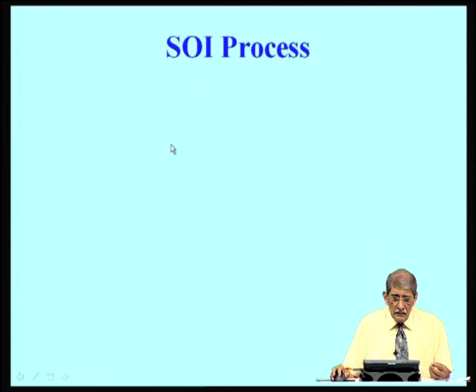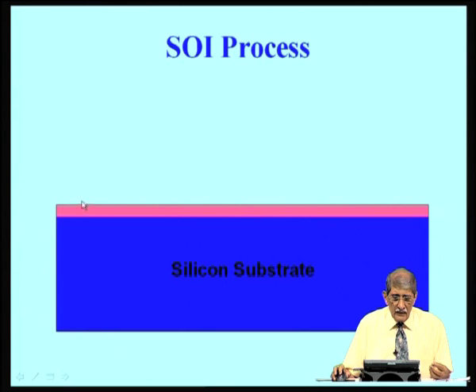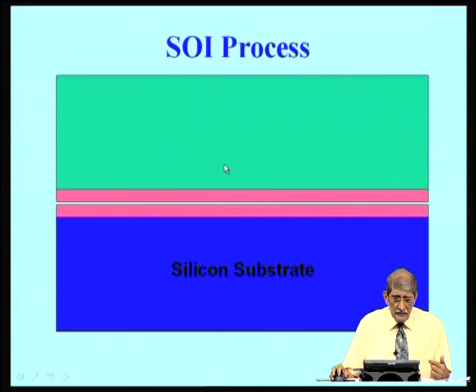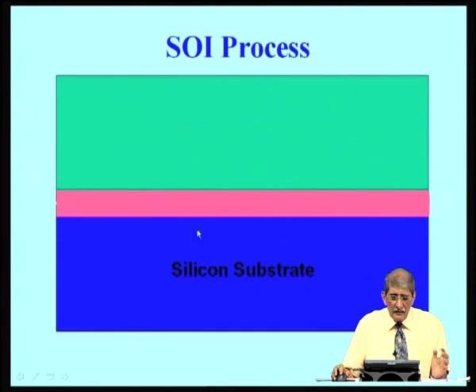Take one wafer, oxidize the wafer, okay, the process to make the SOI layer. Take another wafer, oxidize it and bring them closer together. See this top silicon, bottom silicon, both with oxide grown on them, put them together and apply pressure, maybe 1 atmosphere pressure or more. You can see this gap between them will close. Bonding, they merge together.